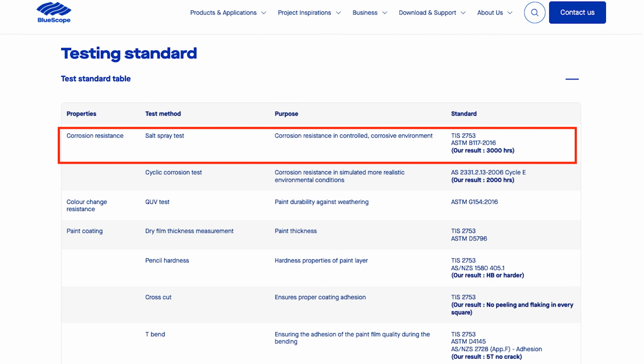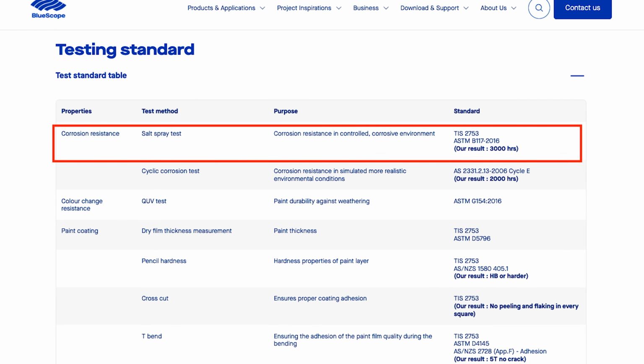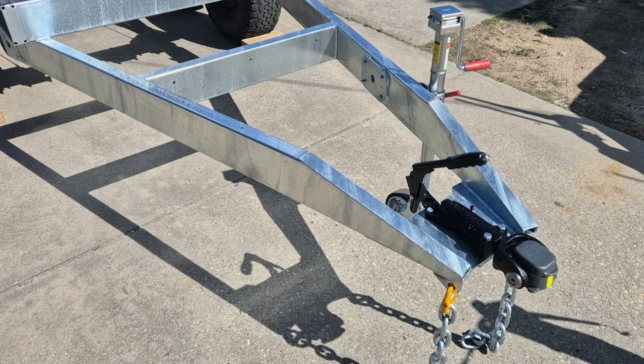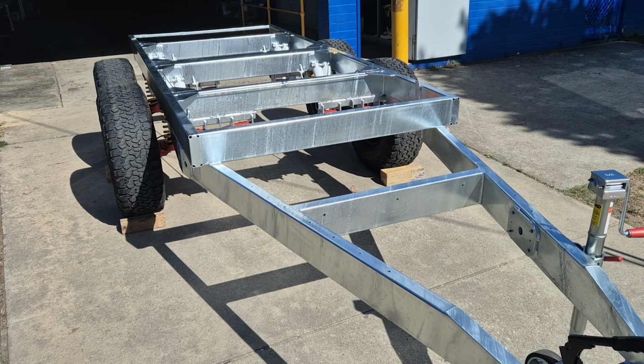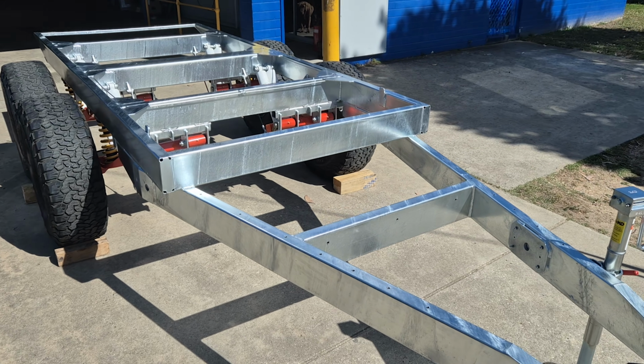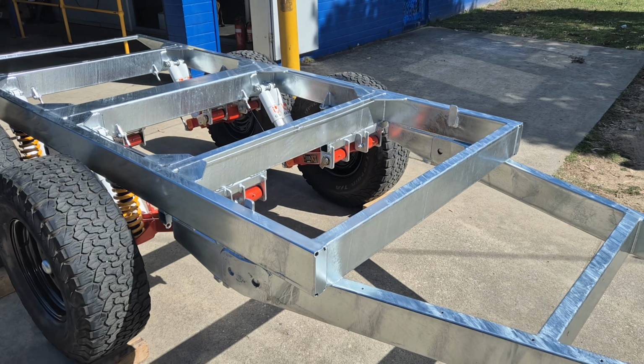These probably don't mean much to you now, but let's give you some examples that you can relate to. We all know ColourBond steel in Australia, and according to BlueScope's own technical data, ColourBond steel is rated to last 3,000 hours in this salt spray chamber. To give you an example more related to a caravan and trailer, the best heavy-duty hot dip galvanization at 85 microns will not last much longer than 1,000 hours in this chamber before it starts rusting. So it is a very aggressive and harsh environment in that chamber.